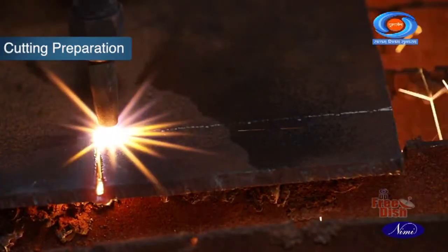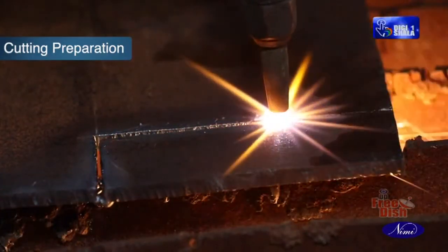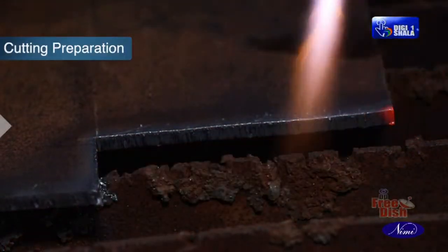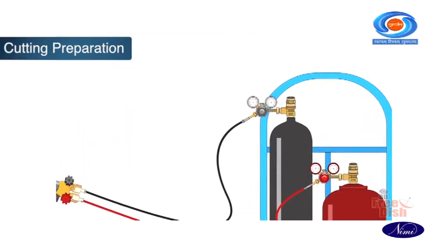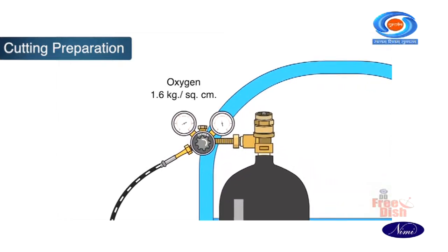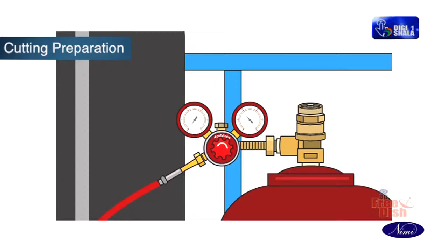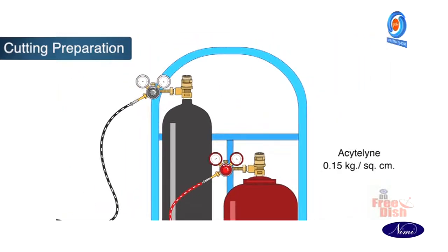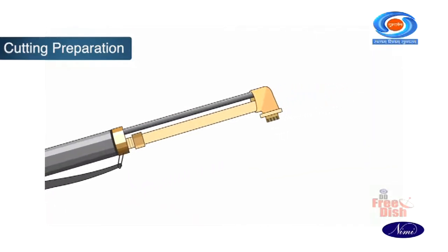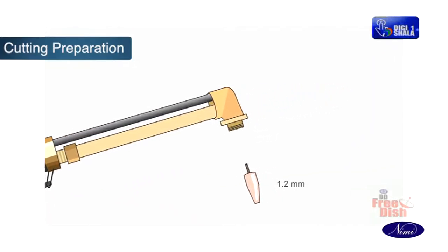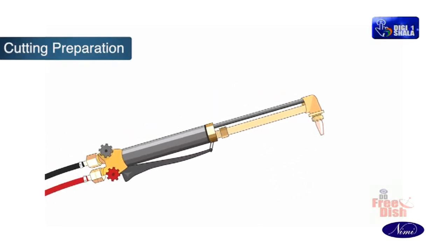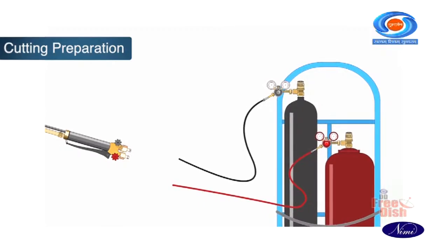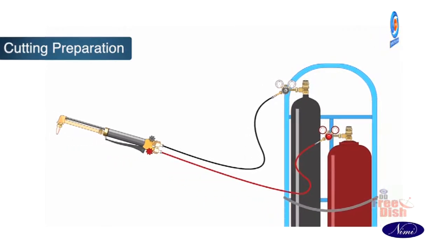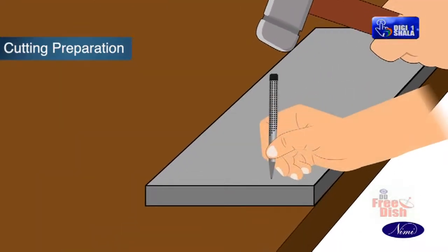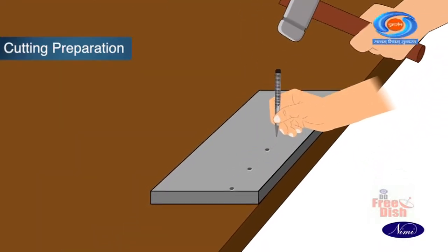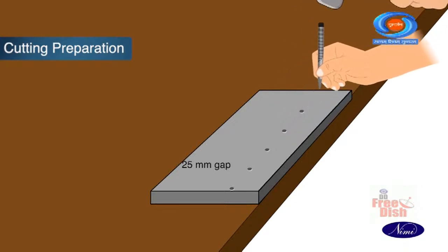Now let us see the procedure of straight cutting of a 10 mm thick MS flat manually. Set the gas pressure to 1.6 kg per square centimeter for oxygen and 0.15 kg per square centimeter for acetylene. Fit the correct cutting nozzle of 1.2 mm dia orifice cutting nozzle. Set the gas welding plant with a cutting blowpipe and cutting oxygen regulator. In a 10 mm thick MS flat, mark and punch the straight lines 25 mm apart.